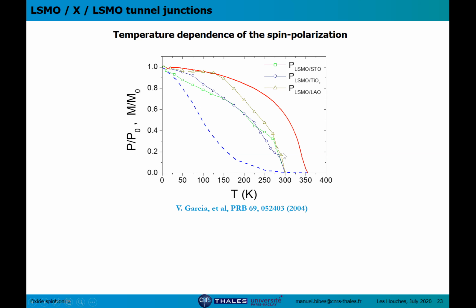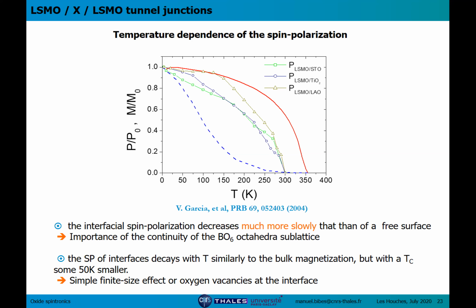At the interface, basically you have a decay that resembles the decay of the magnetization. The red curve is the magnetization, but with a reduced TC, reduced by maybe 50 Kelvin. But it's still much less fast than the decay of the spin polarization of the interface. And this is probably due to the fact that at the surface, you don't have a continuity of the manganese oxygen octahedral sublattice. And so the magnetism is more disturbed than at an interface with these oxide barriers.